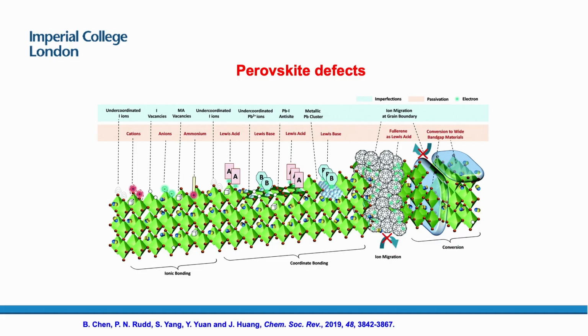So perovskites, this is the problem with perovskites. This is a quick surface sketch of a perovskite, and basically this perovskite surface begins to degrade, and this is where we need to, what we call, passivate. We need to add layers or chemicals that will help the passivation. This is the key question to answer for stability reasons.